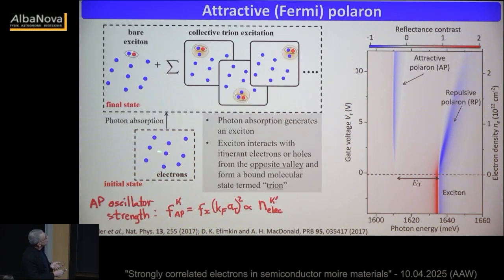Then we send a photon, and once the photon is absorbed, we generate an exciton, just like I mentioned to you. But the exciton in the presence of the Fermi sea is not an eigenstate anymore, because excitons interact with the electrons. This interaction actually leads to formation of a bound state called a trion, if the exciton and electron are in opposite valleys. Now that there is this possibility and this interaction, my cheapest guess for what the eigenstates are would be a superposition of a bare exciton sitting on these electrons together with the collective excitation of trions that the exciton forms with any one of the electrons. So it's a collective trion-like excitation. This superposition is what we refer to as the attractive polaron. It is this resonance that appears. The repulsive polaron is the orthogonal resonance to this.